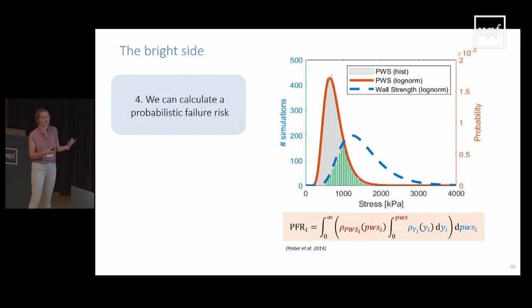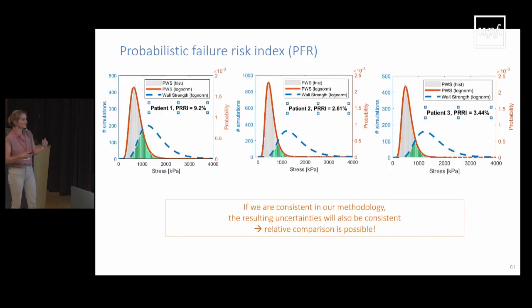And then fourthly, once we have identified these uncertainties and we have a way to propagate them through the system, we can indeed calculate our probability of a certain peak wall stress and our probability of a certain wall strength for a specific patient. Basically, instead of having an absolute or deterministic failure risk, you can make a probabilistic failure risk, which is the area of overlap between those two curves. So the more overlap, the more chances you have that you are at risk for a dissection or a rupture.